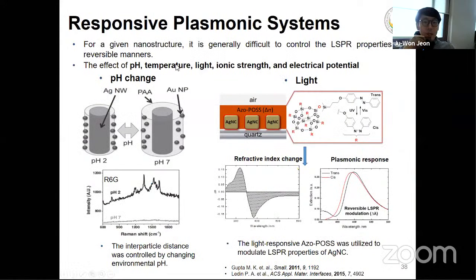So it is possible to synthesize various plasmonic structures with specific LSPR properties through well-defined synthesis techniques. However, for a given structure, it is difficult to change the LSPR property in a reversible manner, and responsive plasmonic systems can make it possible to modulate the LSPR property in real time. Responsive plasmonic systems can be realized by using various stimuli such as pH, temperature, light, ionic strength, and electrical potential. Our group previously demonstrated plasmonic systems by changing the pH and the light.